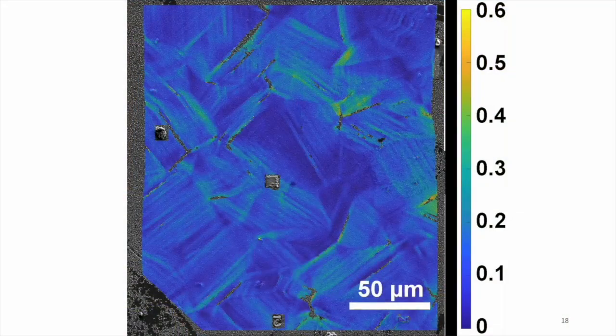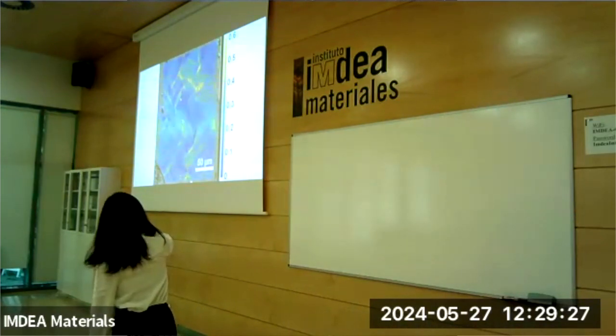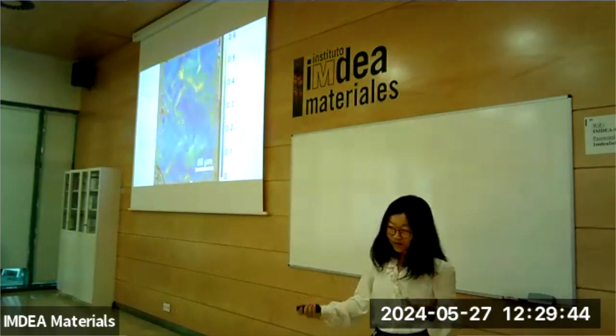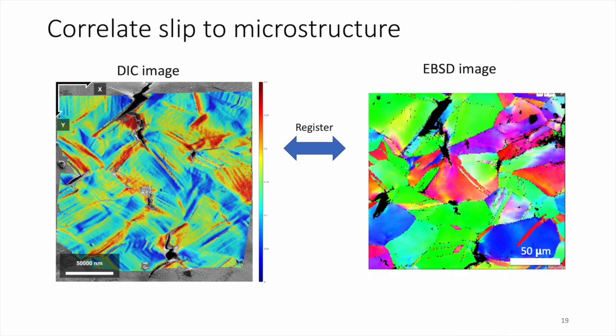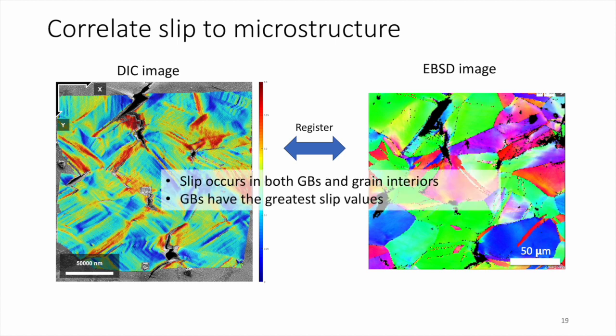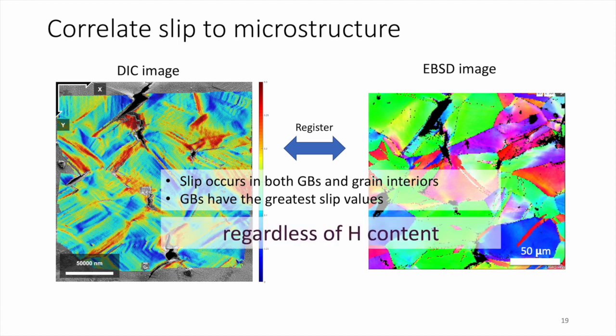First, there are some lines that are parallel together. Second, you have some lines with very bright colors localized in some regions. Where are they? Are they inside of grains, or at grain boundaries? So microstructure-wise, where are they? We correlated this with our EBSD, and we found that the slips occur both in the grain boundaries and in the grain interior, with the grain boundaries having the greatest slip values. And this is true regardless of the hydrogen content.